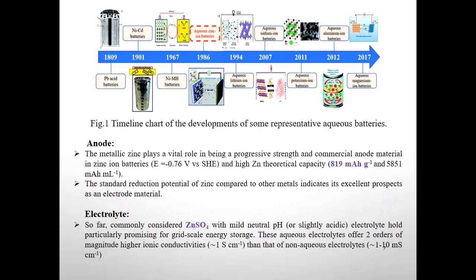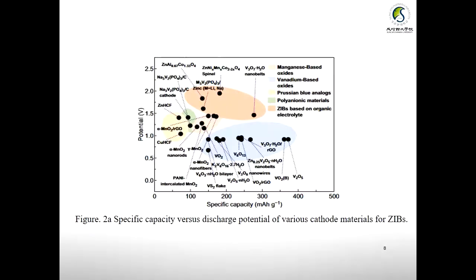Commonly we are using the zinc sulfate electrolyte with a mild pH, which shows a particularly promising application for grid-scale energy storage devices. This aqueous electrolyte offers two orders of magnitude higher ionic conductivity than that of the non-aqueous electrolyte.